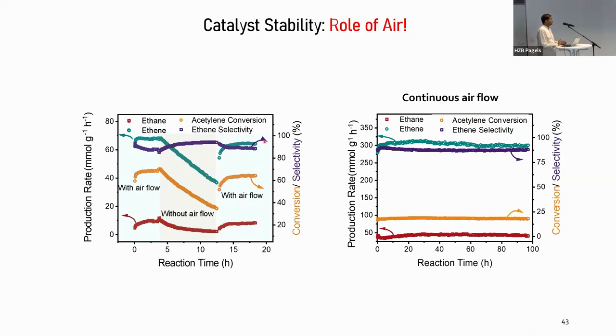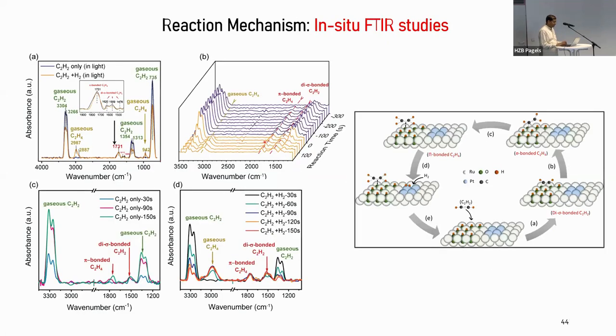Which was a very strange result. Why will oxygen play a role in hydrogenation? So then we try to understand what could be the reason. And for that, we carried out in situ FTIR studies and a lot of XPS studies. And what we realized is, so we thought it's the carbon black onto which you have RuPt, and we thought the RuPt is your reducing site and nothing else. That was our typical understanding.